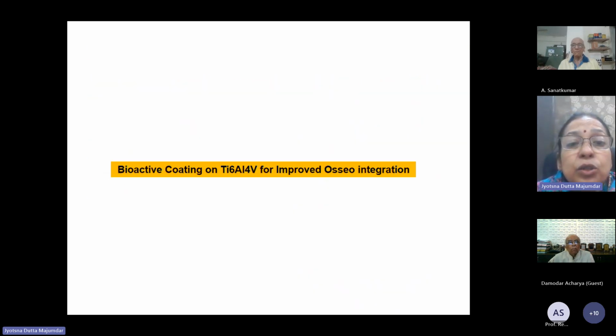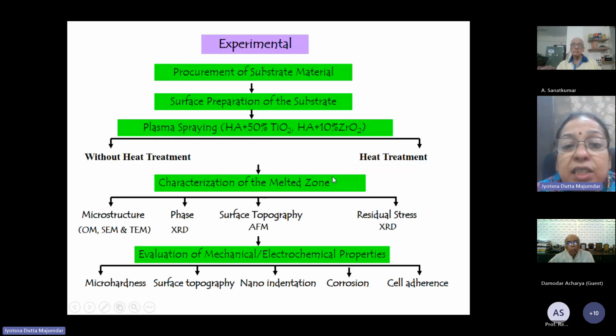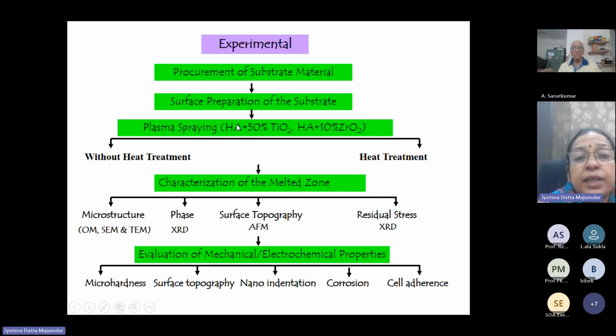Now, as I mentioned, bioactive coating on Ti6Al4V for improved osseointegration, where we used two different types of materials. Hydroxyapatite is a very common material, which is basically applied on the surface by dip coating or by sol gel coating, but we use the plasma spraying technique for development of hydroxyapatite, a slightly modified hydroxyapatite, because hydroxyapatite is very soft in nature. It gets dissolved to a very large extent. The dissolution rate of hydroxyapatite in human body fluid is very high. In addition to that, the wear rate of hydroxyapatite is also very high. It is very soft in nature.